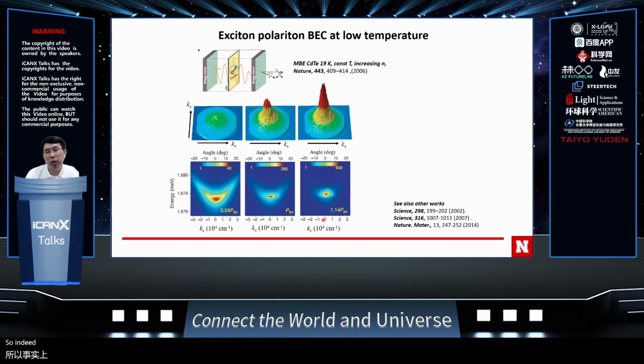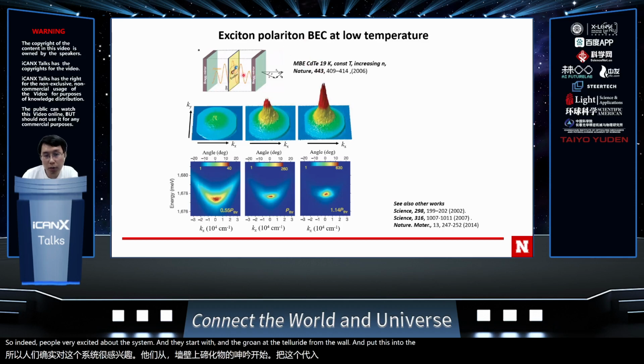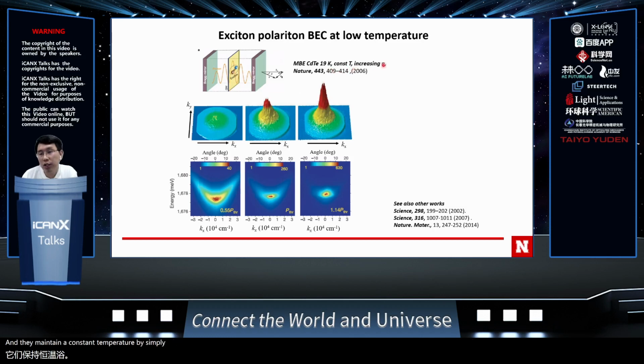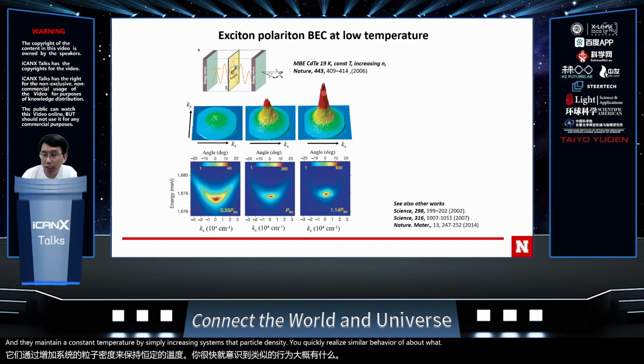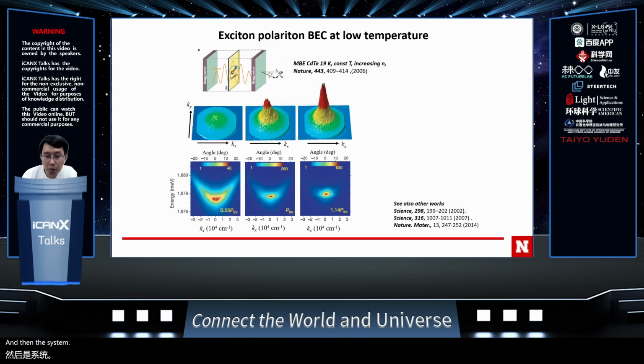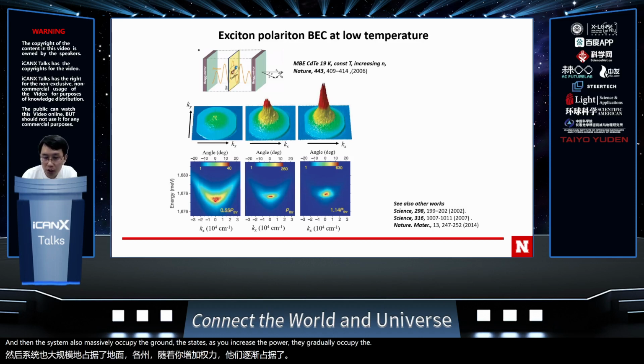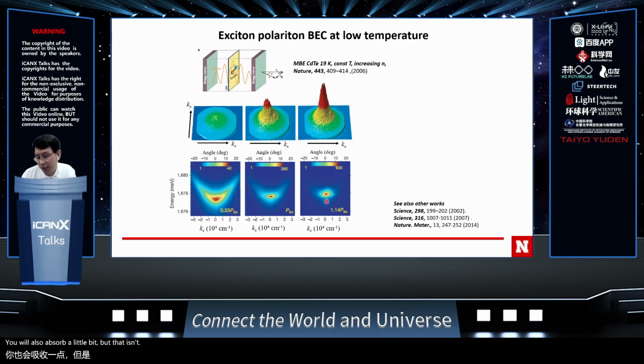So indeed, people are very excited about the system, and they started with an MBE-grown cadmium telluride quantum well and put this into a DBR dielectric cavity. And they maintain a constant temperature and simply increase the system's particle density. You quickly realize behavior similar to a Bose-Einstein condensate. The system also massively occupies the ground state. As you increase the pump power, they gradually occupy the energy minimum states of the lower polariton. You will also observe a little bit of blue shift, but that is essentially generated by the exciton-exciton interaction, which is ideal for some of the quantum applications.